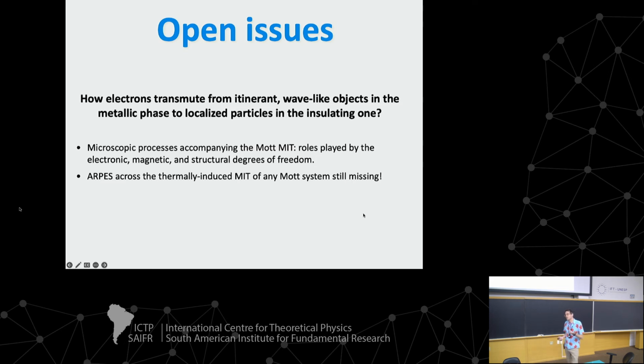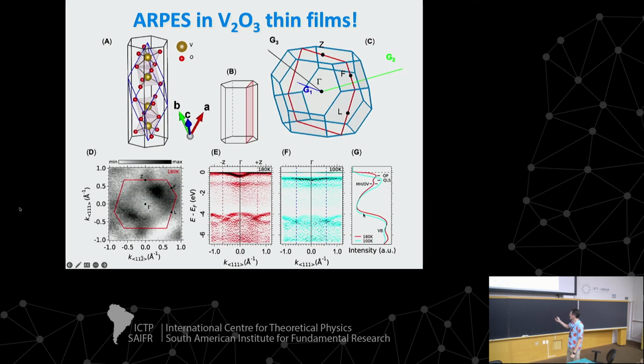So the way we went around that is to measure thin films. In thin films, the material itself is anchored by the substrate, and this prevents the metal to insulator transition from destroying the sample, while still showing the metal to insulator, antiferromagnetic, and structural transitions, but the system is not destroyed. So we measured in thin films, and this is a first glimpse of the answer.